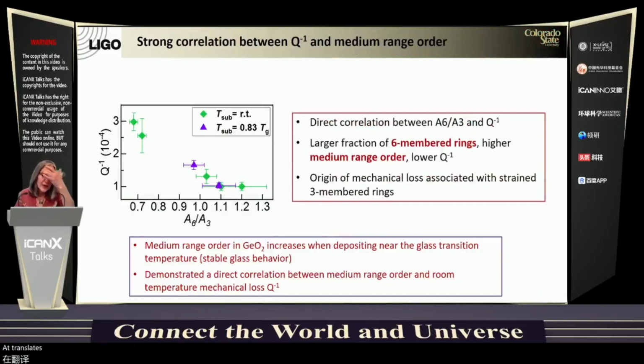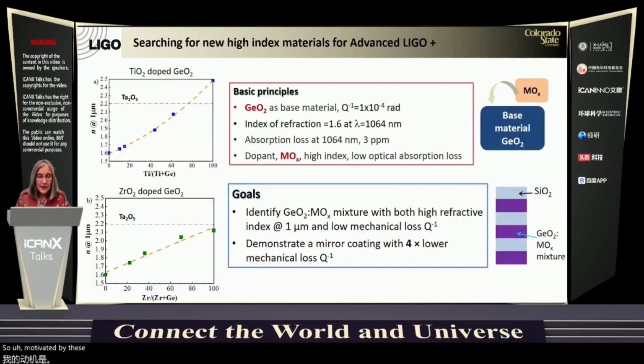So how does this relate to mechanical loss? Well, the higher increase in medium range order leads to a decrease in mechanical loss. So motivated by these results, we are now doping germania with different dopants.